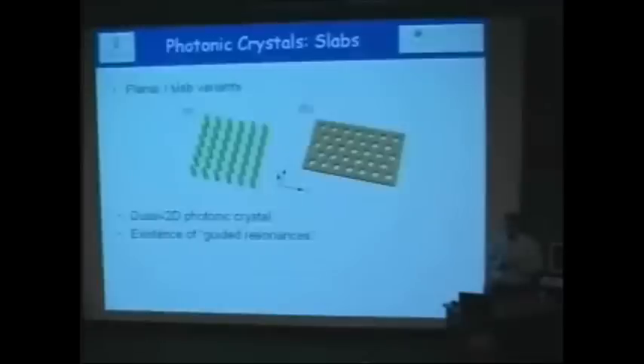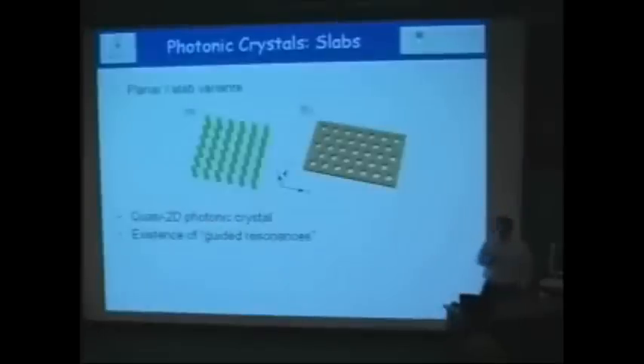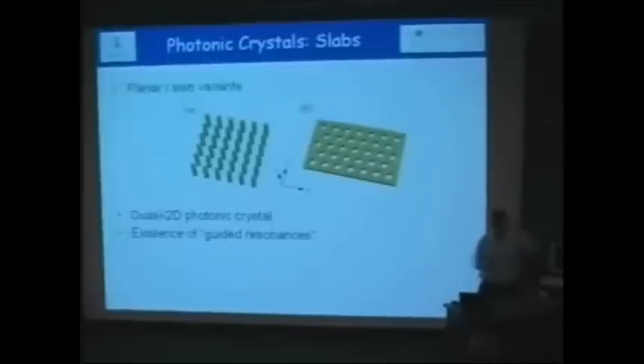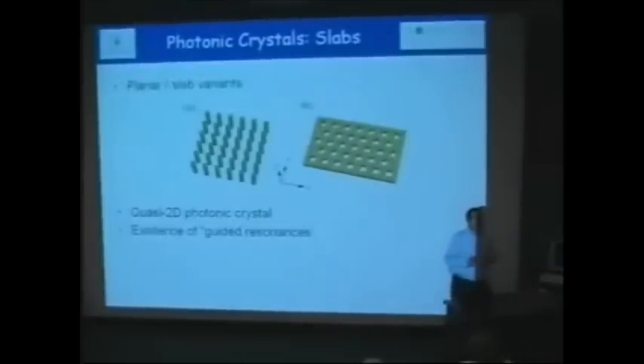What we're going to talk about is different. We're going to talk about photonic crystal slabs. As you could see, you could create a slab, say in silicon or another dielectric, and then you create a periodic structure of either holes or rods. Depending on the design, both of them are regarded as a photonic crystal. Now, this is quasi-2-dimensional because within any plane, the periodicity creates a 2-dimensional photonic crystal, but at the same time, the material itself creates some difference in the other dimension, namely the Z dimension. So over here, for example, if it's a silicon device, you have water above or water below, or maybe air above or air below, and that difference in the height creates effectively a 3-dimensional structure.